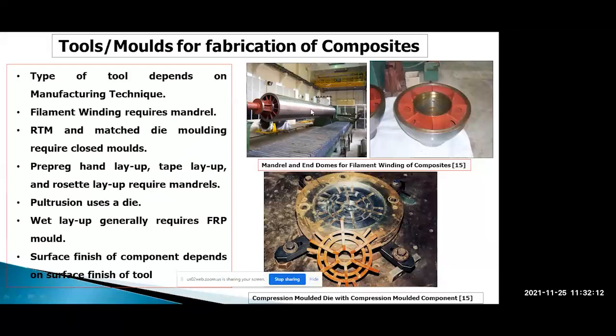First is the dimension. A little taper for extraction we give. This is over 8 meters in length and almost 1 meter in diameter. So 2 mm on the diameter we give as extraction taper. Plus, for surface finish we use almost N6 grade. Only then do we get a smooth inside surface of the composite component. This is the die for compression molding. This is the compression molded component. This is the die.